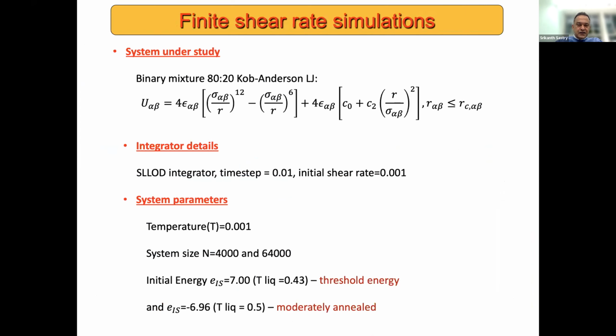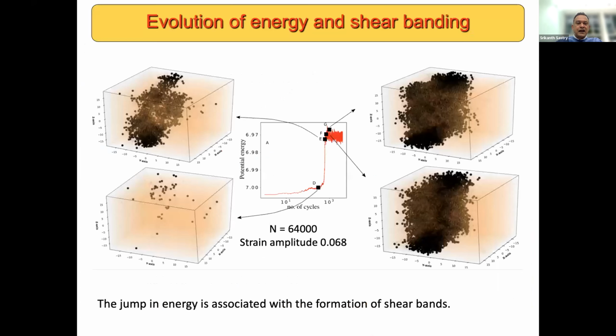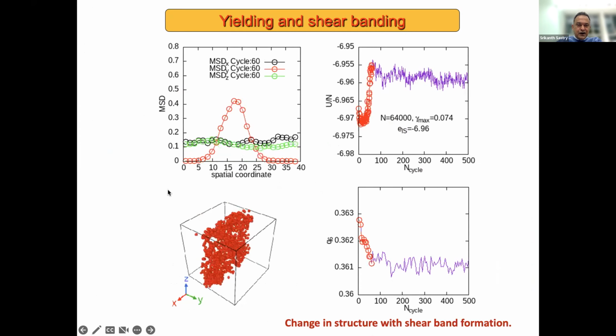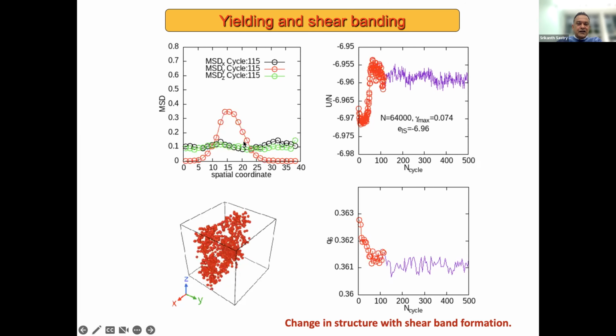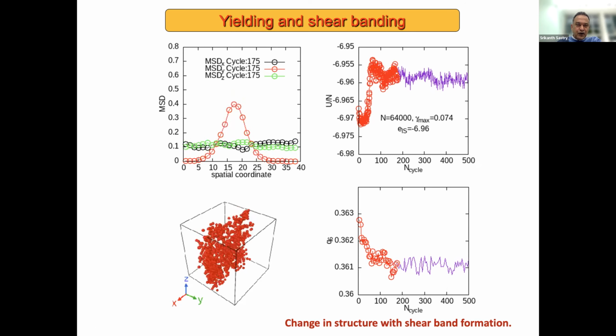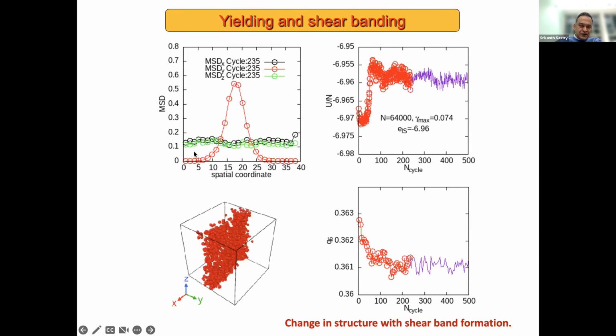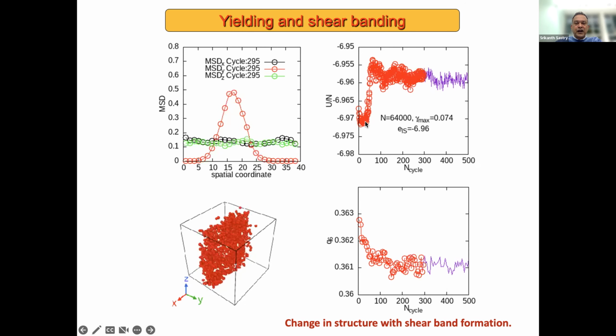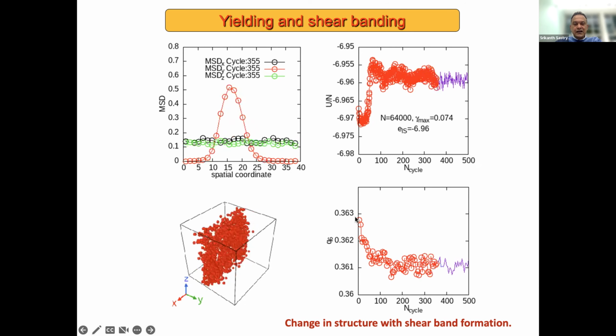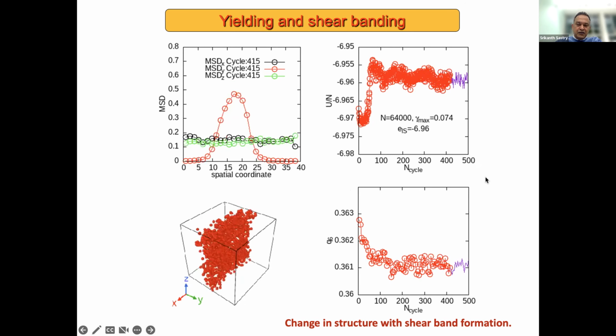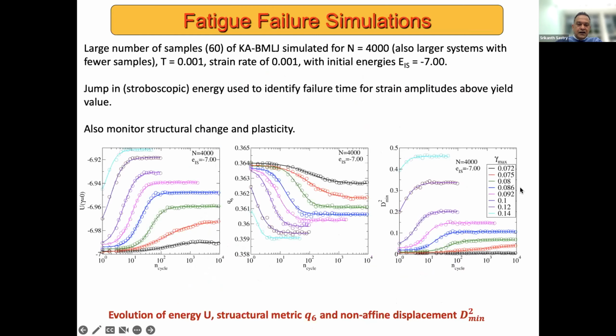So we've been recently looking at all these phenomena using finite shear rate simulations. And once again, to illustrate what I said, these sudden jumps in energy are accompanied by the formation of shear bands. And these are shown also in this video, where the graph shows the amount by which particles move over a given cycle. And you see the emergence of this peak in the red curve at the point where the energy begins to jump. Equally interestingly, there are structural changes you can monitor, and these have clear correspondence with the behavior of the energy and the formation of shear bands.